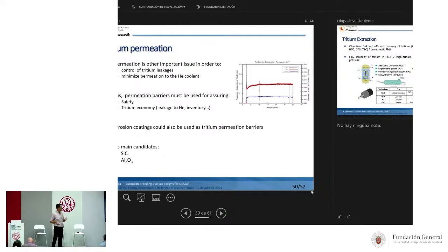What we are thinking is to use the coatings for corrosion also as anti-permeation barriers, because at the end it's ceramics, and these ceramics can act also as anti-permeation. And for that reason, we are studying also the silicon carbide and the alumina coating.